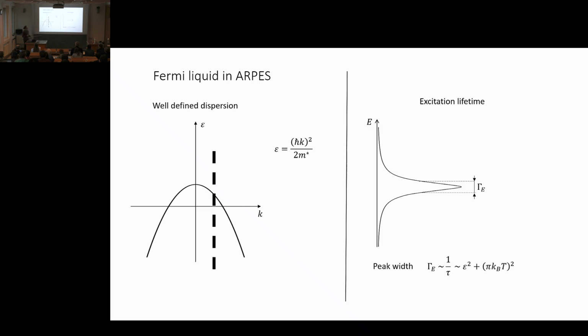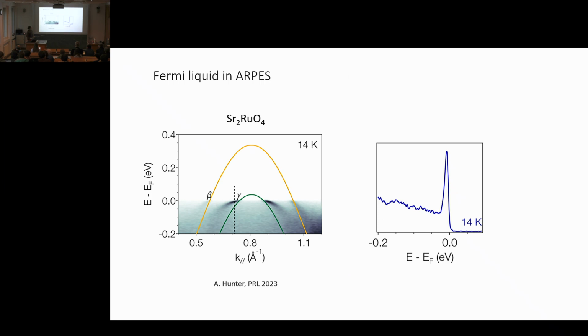And what we are quite interested in, if we take a single cut along a single momentum, we get the energy dispersion for our quasi-particle. In particular, we look at the width of our energy dispersion, which should be Lorentzian. This is again proportional to epsilon squared plus T squared, which we've seen from the Fermi-Landau theory. And for strontium ruthenate, you might have guessed it already, this works perfectly well at low temperatures.